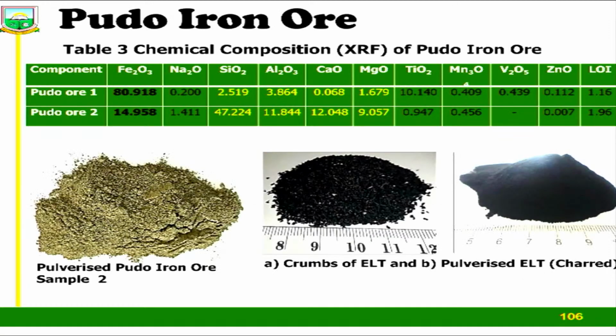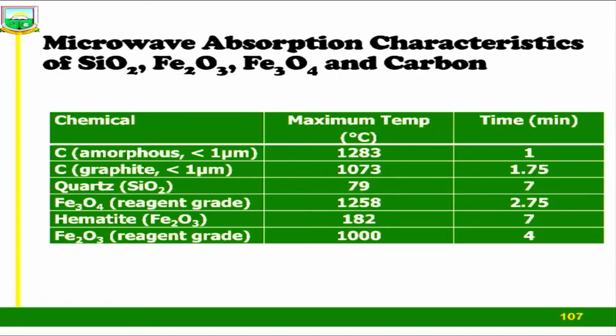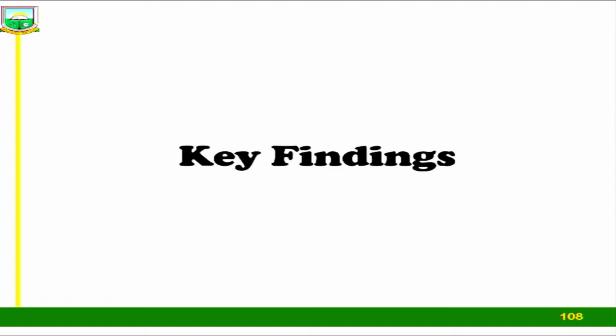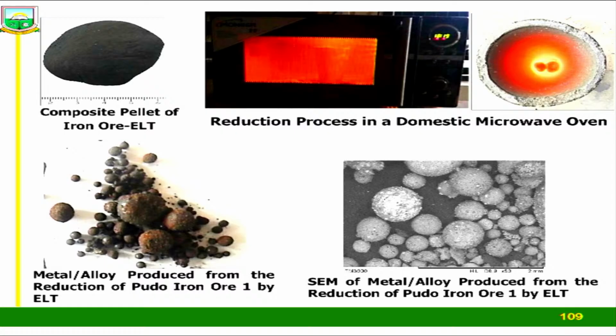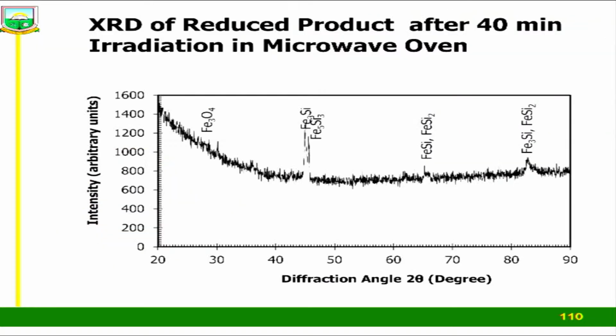Then we went to the Pudo iron ore. The results are not very different, so let me quickly go through. The key findings that we've got over there: if you take a look at this, we used just the microwave. We didn't have access to the horizontal tube furnace. And this is the metal that we produced. If you can see, we tested for this up to about 97 to 99% metallic iron. We also produce ferrosilicon from the process using the same raw materials.